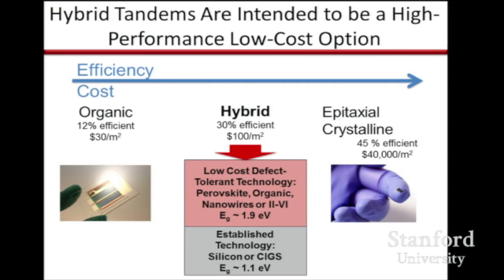And I say silicon because practically, right now, more than 85% of the market is based on silicon, and huge factories are built in China. They've got great economies of scale, and I've learned the hard way that around here it's going to be awfully hard to form a startup and raise the capital you need to compete when they're at that scale. So if you can basically upgrade silicon by putting something on it, you're not proposing to shut down the factories that have been built. You're just proposing to add some tools into them and take silicon or CIGS from where it is up into the mid-20s for efficiency or even higher.